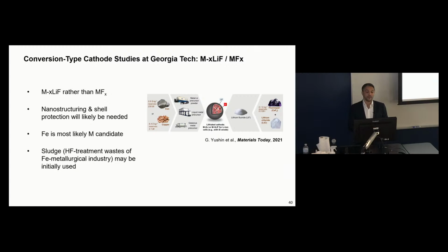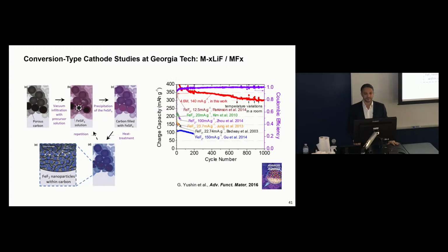And in addition, there is a huge amount of waste products of the metallurgical industry. And so this iron that is already treated with HF, that has fluorine, is available at essentially negative cost. You have to pay to get rid of it. And so if you can use it as an input material for your metal fluoride particles, that would be outstanding. You can have very low cost production. And then one of the challenges, as I mentioned, is the segregation of the particles, and the high resistance of the lithium fluoride could be overcome if you simply nanoconfine it.